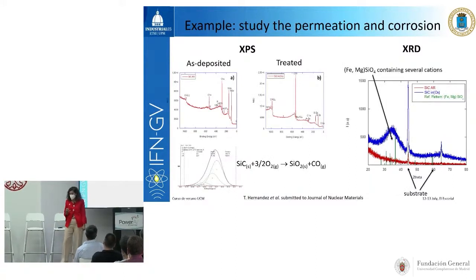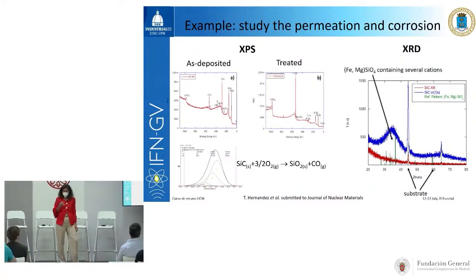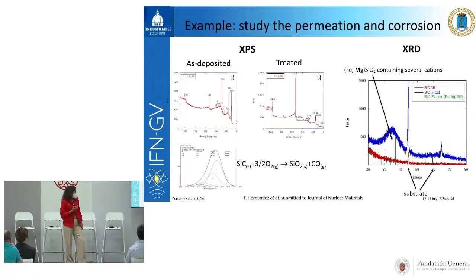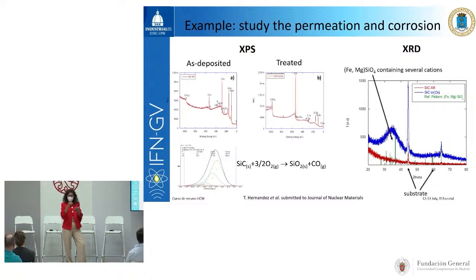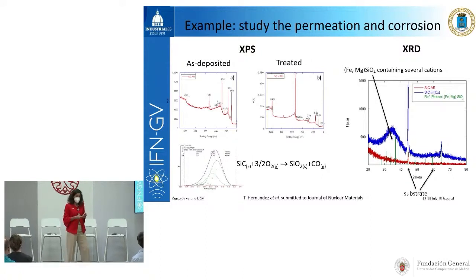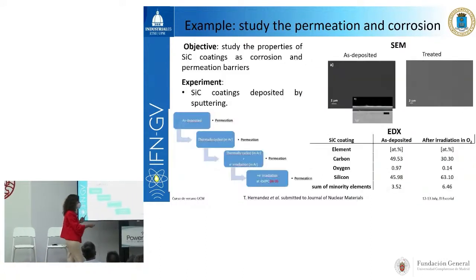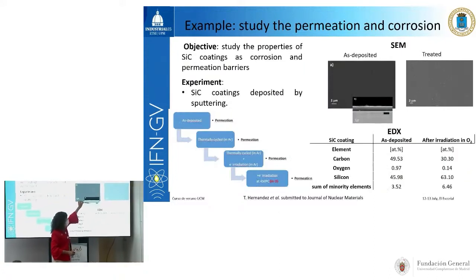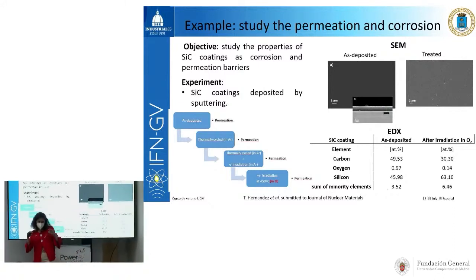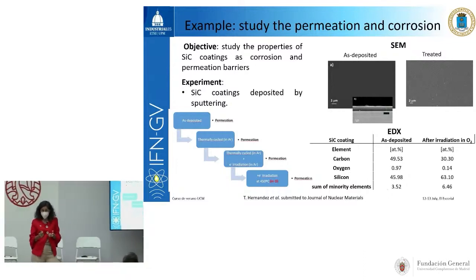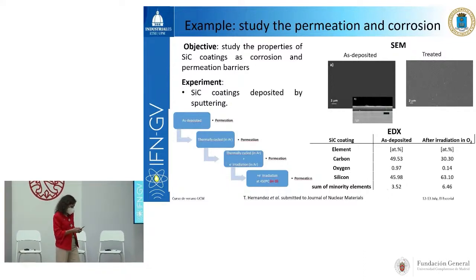We formed secondary phases. Because if you form secondary phases, it will mean that the material is not a real barrier to lithium. You know, lithium is a very small ion which can diffuse into the material, as happened with the standard aluminum oxide. And if you have lithium penetrating through the barrier, then you may be in trouble. Here you may see the interface, this is the coating, this is the substrate, so if the lithium penetrates here, you are going to have a problem at the interface, or even the lithium penetrates into the Eurofer steel, which is very bad news, because of corrosion.